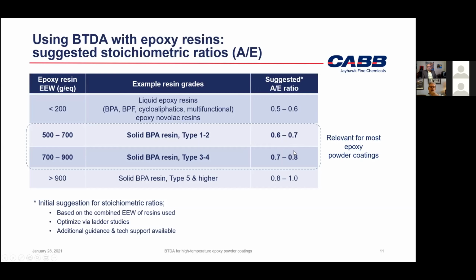There's another thing that I can add here. As formulators, we look into our formulating toolkit, and we try to achieve a balance of performance features, and it could be chemical resistance, heat resistance, flexibility, elongation properties, thermal cycling type behavior. And the way we set this up, we wanted to look at a survey of different equivalent weights, which translated into different molecular weight epoxies, just to see the response and see where these things fit in. Because with formulation, it's like cooking soup, or making a nice sauce or something. A little bit of this, a little bit of that, and you look for the balance of performance. And what we try to do here is determine the fundamental performance with different molecular weights, so that a formulator could see that and incorporate it into the needs that they have for their formulation.